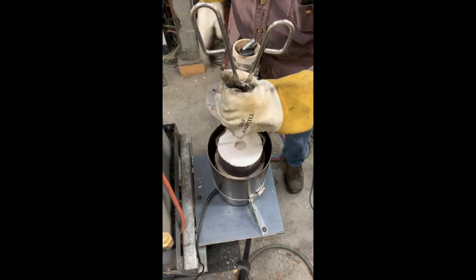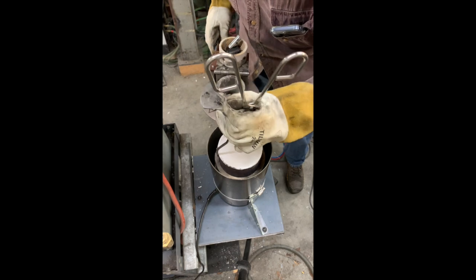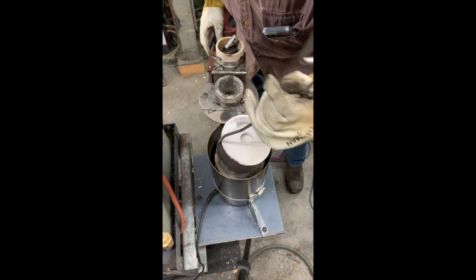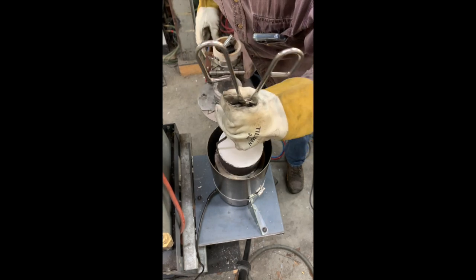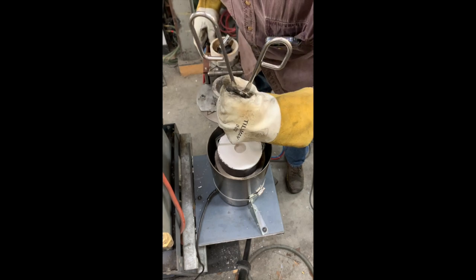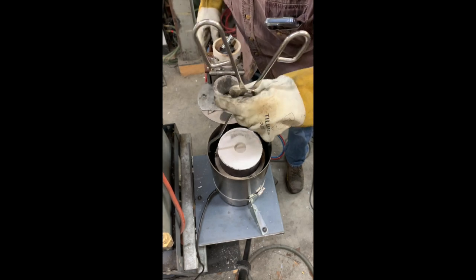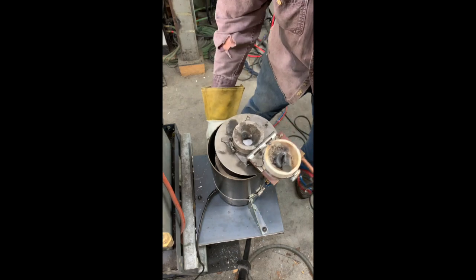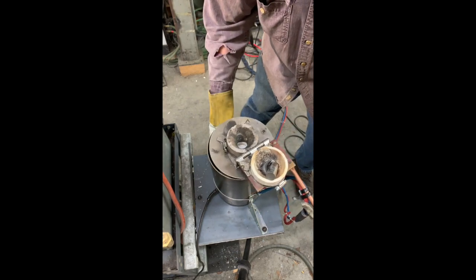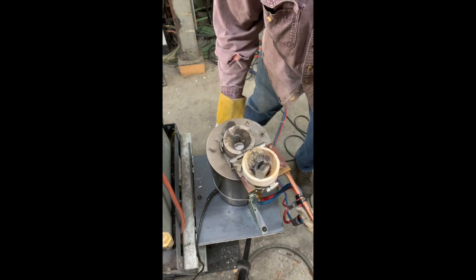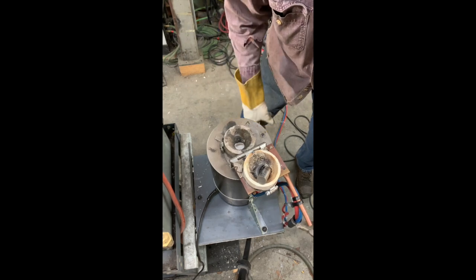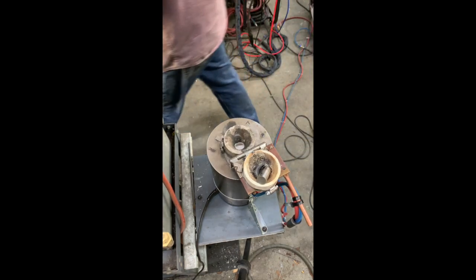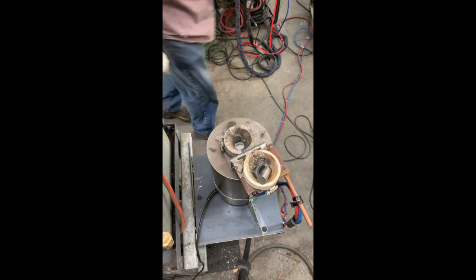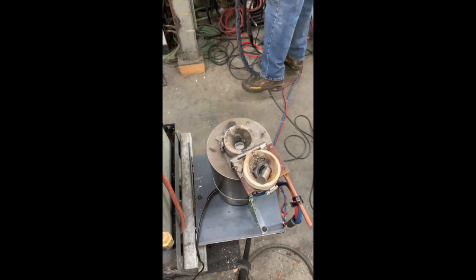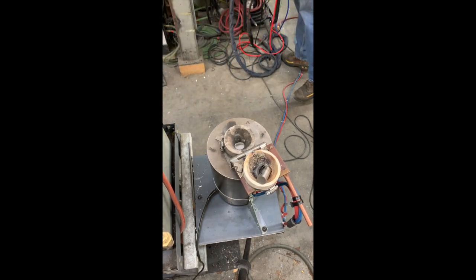1200 degrees Fahrenheit right now, so can't just reach in there with my fingers and grab it and put it in there. So a little fiddling around to make sure it's sitting nice and correctly in that machine. When I turn the machine on, the flask starts to spin. So this is a centrifugal casting machine. The flask is spinning at about 900 RPM.